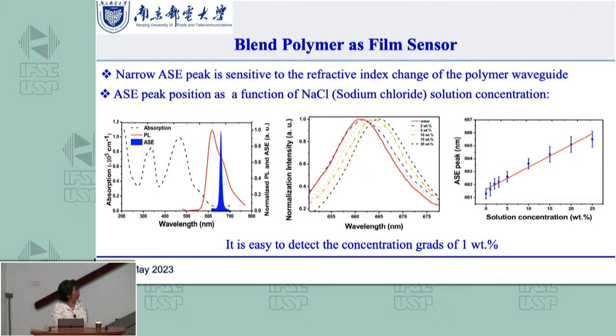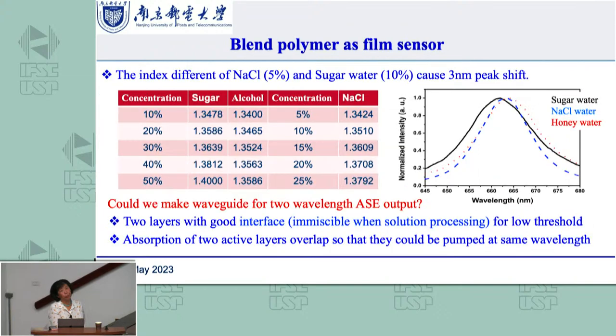Look, that is water with different concentrations of salt. You can see the clear shift of the peak, and if you plot the peak shift, you can see it's very clear. This work we did before the pandemic.